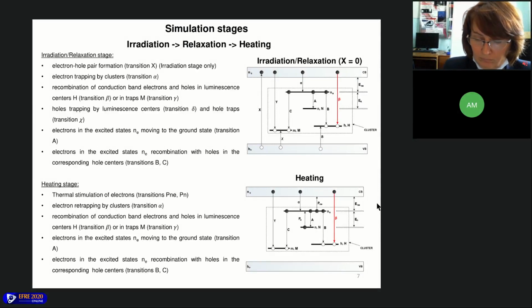On the slide, the upper figure shows possible transitions on irradiation and relaxation stages, except for transition X, which is possible during irradiation stage only. At irradiation stage, electron-hole pairs are formed, then conduction band electrons and valence band holes are captured by corresponding centers. Also, electrons can recombine with holes in hole trapping centers. At the relaxation stage, electron-hole pairs formation is absent, remaining delocalized electrons and holes continue being captured by corresponding trapping centers. At the heating stage, thermal stimulation probabilities increase due to temperature growth.